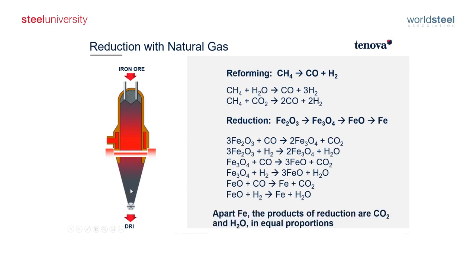Differently from the blast furnace process, in the direct reduction shaft the metal and the material do not reach the melting point. The material is discharged at 700 degrees, so it retains the form of pellets, and then it can be charged either hot into a downstream reactor, namely an electrical furnace or a submerged furnace of sorts, and then molten and transformed into steel. So in the most normal way of operating a direct reduction plant, there is a lot of hydrogen already in the process.